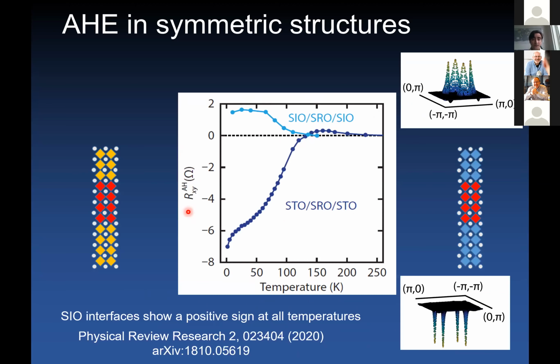This is not an accidental temperature at which this occurs. So this is the sign of the anomalous Hall effect as a function of temperature, measured for strontium titanate, strontium ruthenate, strontium titanate, and strontium iridate, strontium ruthenate, strontium iridate, between 1.5 Kelvin and 250. And you see that this negative sign and this positive sign is observed very systematically across all temperatures. And this is a direct indication that we have manipulated a topological structure in momentum space. So we went from a set of prevalent poles of Berry curvature that had a positive contribution to a prevalent set of poles that gave a negative contribution.